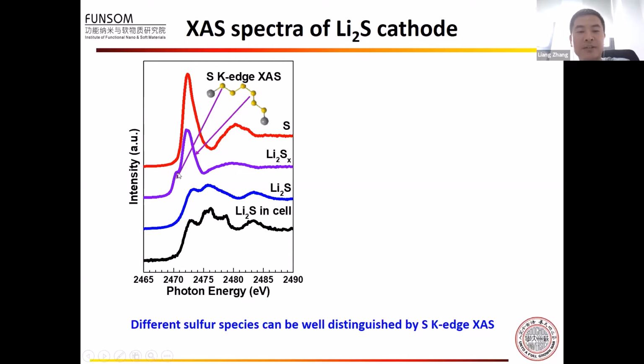By using this pre-edge feature, we can distinguish the sulfur and the lithium polysulfide. For lithium sulfide, the spectrum is very different from that of the elemental sulfur and lithium polysulfide. This is because lithium sulfide is an ionic crystal, and its crystal structure is very different from elemental sulfur. One interesting thing is that for the lithium sulfide in the in-situ cell, besides the main feature of lithium sulfide, we also find two new features at higher photon energy. We propose these features are related to the oxidation of the lithium sulfide when contacting with the electrolyte.